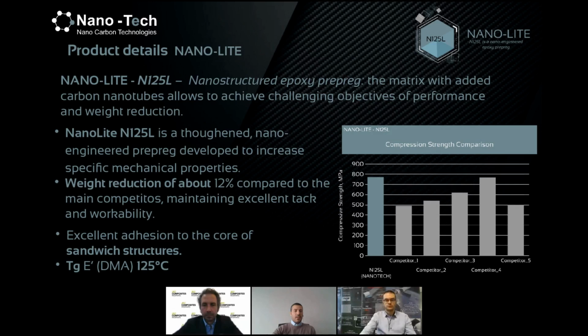Then we have the Nanolite NI25L, a nanostructured epoxy prepreg with about 125 degree Tg. We use nanoparticles in order to have a very particular rheological behavior of the resin that allows us to obtain prepreg that is lighter. So you can have a weight reduction of up to 12% compared to the main prepreg on the market with the same layup. Then we use the nanoparticles to increase the overall mechanical properties of the composite, in particular the compression strength. As you can see here, a comparison between most of our competitors. We are one of the best in class in compression properties. This test was done on high strength carbon fabric.